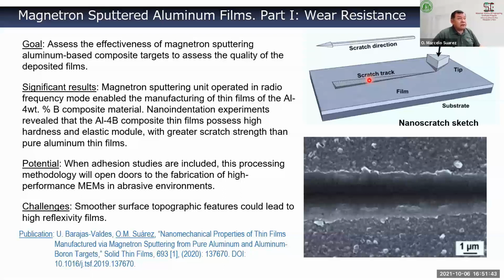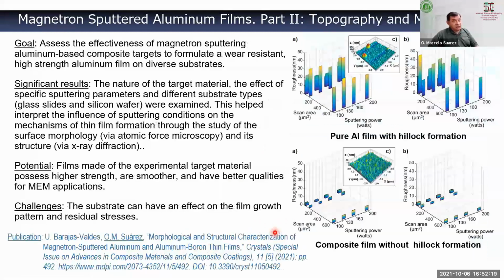We found out that the Young's modulus of the film deposited from the composite target was really high, maybe twice as high as the pure aluminum one. So the wear resistance was high too. After all that analysis, we produced one paper a few years ago, actually last year. And we continued that work, because that was not enough.